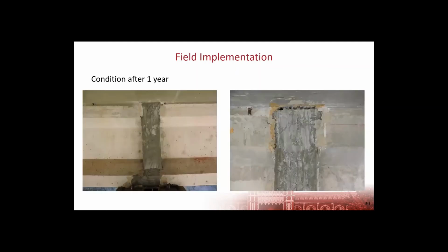We monitored those joints for about a year. After that year, they looked as good as they did the day they were cast. We didn't see any signs of distress around those joints. Here on the right, you can see at the top of one of those joints, there is some airspace, which we think is a result of air escaping, causing some settlement after casting, just because we only had the one fill hole that was fairly small and the air didn't have any way to escape quickly.